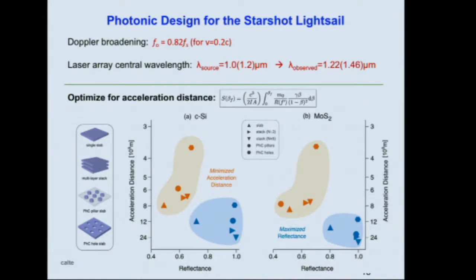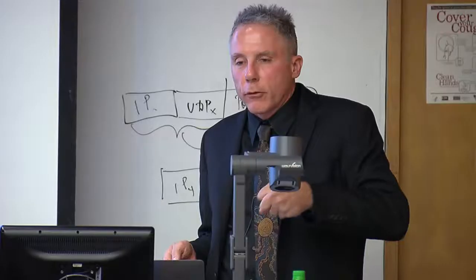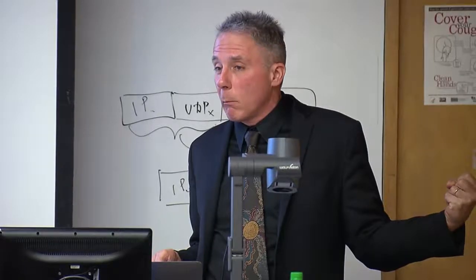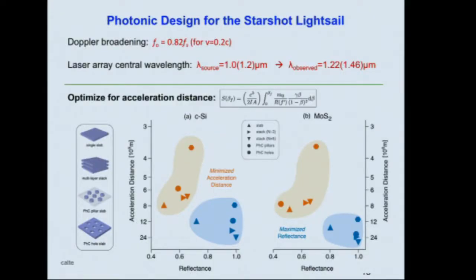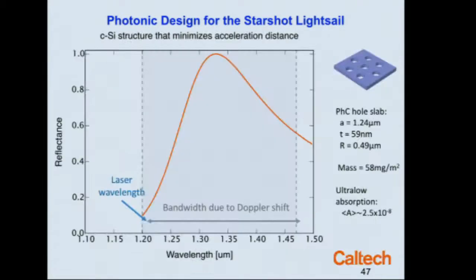And the reason is very simple. By putting holes in the photonic crystal, we take away some of the weight. And so it turns out we can give up a lot of reflectance in our design optimization in favor of getting rid of the weight. And so that has a reflectivity, can reach 0.2 C according to this analysis in even less than 1,000 seconds.